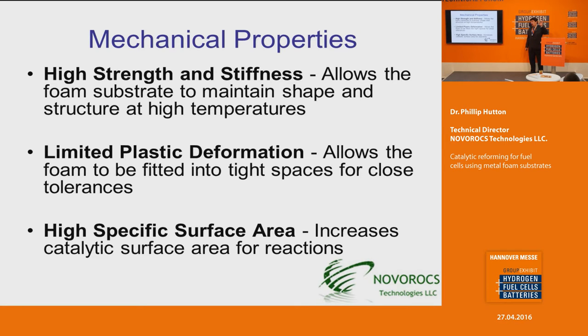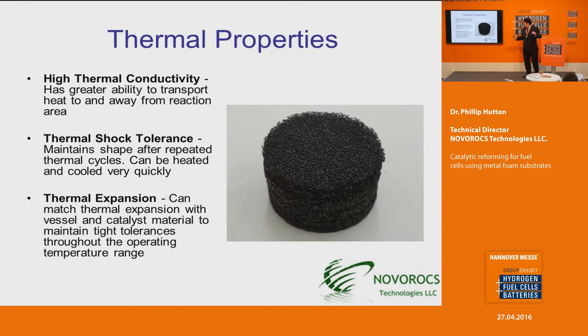High specific surface area. As you can see from this, gases flowing through have a lot of surface area to contact and react. What this does is increase the activity for a given volume for whatever reaction you're looking at, compared to a typical bead catalyst.